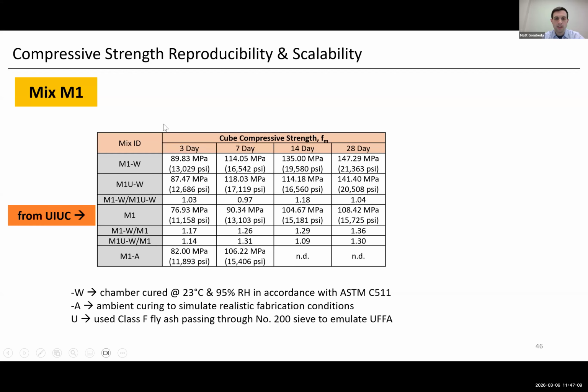So we have one that is chamber cured in accordance with C511. We had one that used a class F fly ash that was sieved through number 200 to emulate an ultra-fine fly ash, which was part of the original development. We recognized that not everybody had access to the ultra-fine fly ash, so we wanted to come up with an equivalent way to produce it with the standard fly ash. And then we also had the dash A ones, which were done ambient. So some of these members you're not going to have the luxury to do in a chamber. So we wanted to also look at the variation in the strength when we had ambient conditions versus ideal conditions in the chamber.